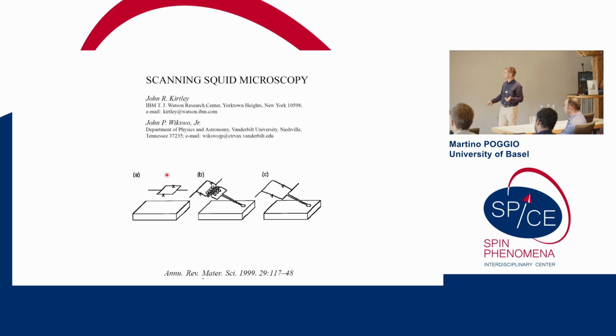In the past, this has been difficult. Let's say it's been difficult to study nanomagnetism with such things because the squid loops were just in practice very difficult to make small. So most squid loops were in the micron scale or much, much bigger. And also, the Josephson junctions that were used, so superconducting Josephson junctions, typically had upper critical fields below 10 millitesla, meaning that essentially you couldn't measure anything in a significant magnetic field. And so for many, many years, these were essentially just used to measure superconductors, superconducting vortices, and so on.